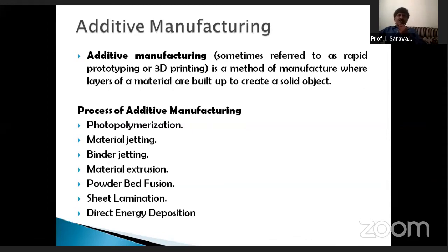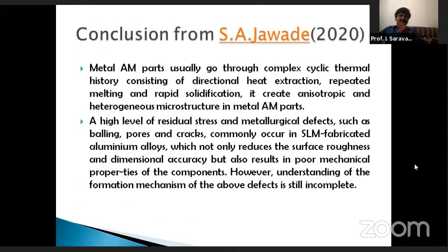Professor S.A. Jauda in recent 2020 has concluded that metal AM parts, that means additive manufactured metal parts, usually go through a complex cyclic thermal history consisting of directional heat extraction, repeated melting and rapid solidification. It creates anisotropic and heterogeneous microstructure in additive manufactured metal parts. A high level of residual stress and metallurgical defects such as balling, pores and cracks commonly occur in SLM-fabricated aluminum alloys, which not only reduces the surface roughness and dimensional accuracy, but also results in poor mechanical properties of the components. However, understanding of the formation mechanism of the above defects is incomplete.